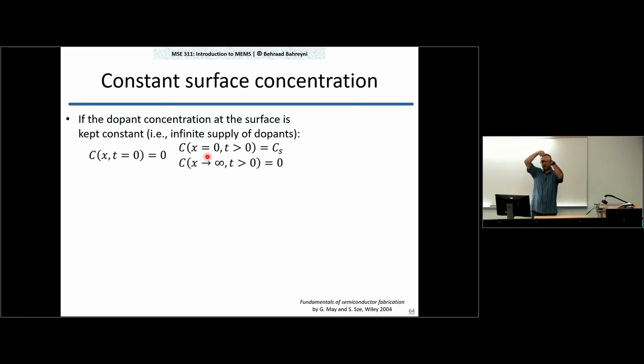And the other point. Well, it's a partial differential equation, and it has a second derivative with respect to x, first derivative with respect to t, so I need one other boundary condition. The other boundary condition is that if I go very, very deep into the substrate, infinitely deep, I expect the concentration to be zero. I don't expect any of the dopants that I'm adding here at the surface to penetrate that deep, no matter how much I wait. If I go far enough, the concentration will be zero. So these are the three, well, the initial condition and the two boundary conditions that I have.